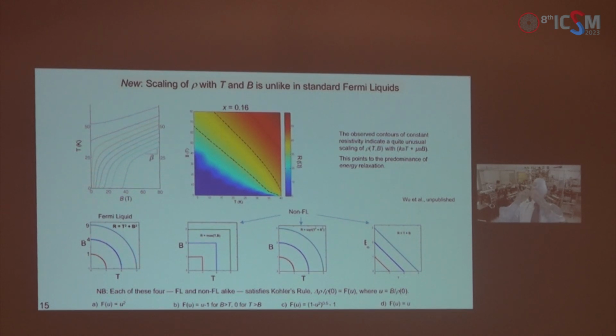Think of the potential of a point charge. It's a function of x, y, and z. But because of spherical symmetry, the potential is constant on every concentric sphere. In other words, you can express it as a function of only a single variable, which is the radial distance. So something like this here: when we plot the contours of constant resistivity, their shape is actually very telling. And what I'm showing at the bottom are 4 scaling laws. The first one is what you expect from a Fermi liquid, and then the other 3 would be like marginal Fermi liquid, the scaling proposed by Jim Analytis and Schechter, and the last one is a sum of the magnetic and thermal energy. And clearly this last one is the winner. It looks the closest to the data.